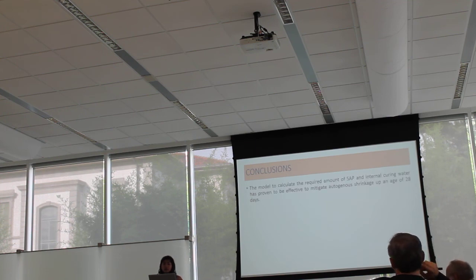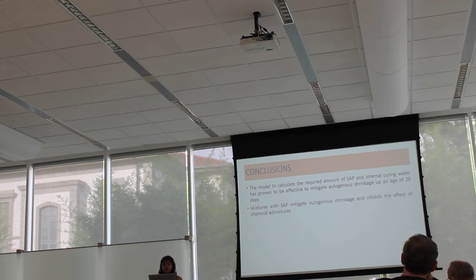For the conclusion, we have that the model to calculate the required amount of SAP and internal curing water, meaning the Powers model, has proven to be effective to mitigate autogenous shrinkage at an age of 28 days. Also, mixtures with SAP mitigate autogenous shrinkage and inhibit the effect of the chemical admixtures.